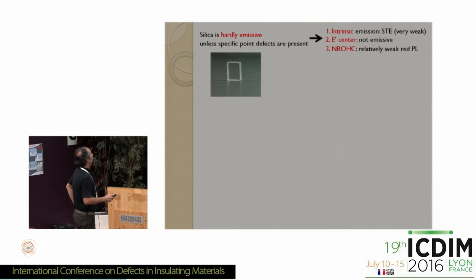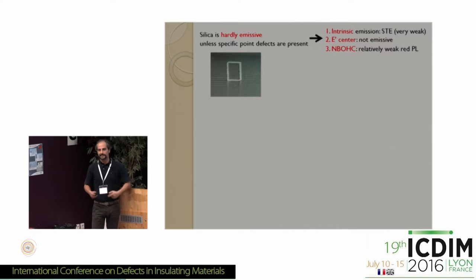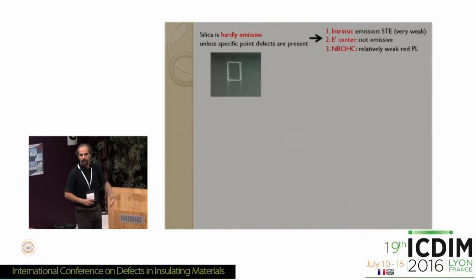Now, why is nanometrically confined silica important? There are many answers to this question, but I'll give you one. Based on what I've been telling you up to now, you should be convinced that silica is a material which is nice for many aspects, but is not a good emitter. Because if you resort to intrinsic emission, then you need to excite silica across the band gap, so with very, very short wavelength radiation, and the emission you get is the emission from self-trapped excitons, which, by the way, has a quantum yield of about 10 to the minus 3, so it's not very intense.